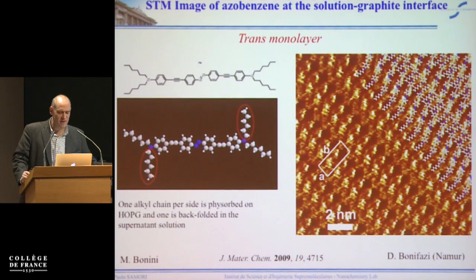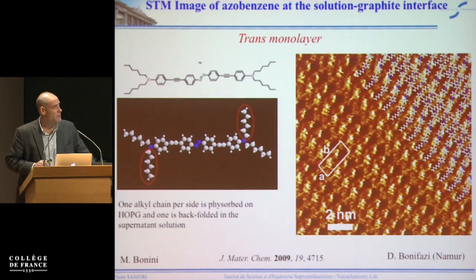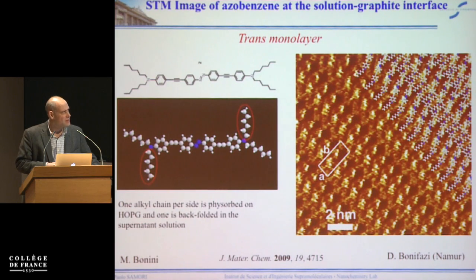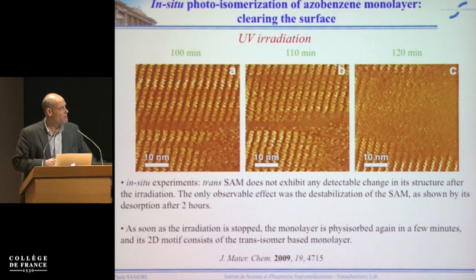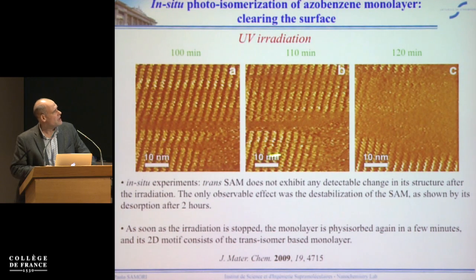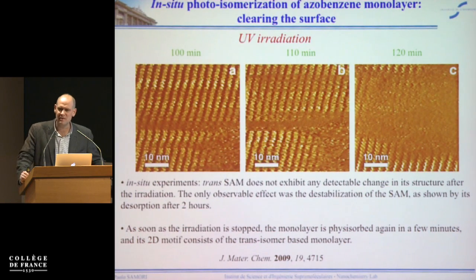Now, why did we decide to focus on the alkyl substituted azobenzene? The reason is because we published a paper in 2009 that was not at all on graphene, just a simple paper done together with Davide Bonifazi about how this kind of molecule was self-assembling on the basal plane of graphite, and looked by STM at their isomerization in situ at the solid interface. What we noticed is that when the molecule was in the trans form, it was forming very nice lamellar structures. While we were irradiating with UV light, the molecules were desorbing out of the surface of graphite. This means that the cis has a much lower energy of adsorption on the basal plane of graphite compared to the trans.